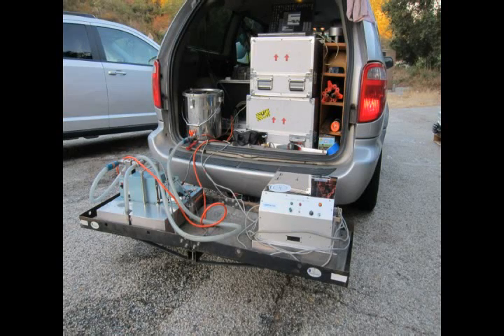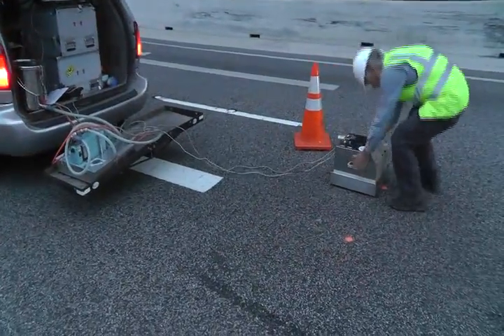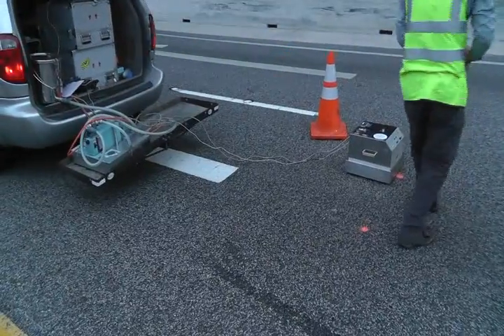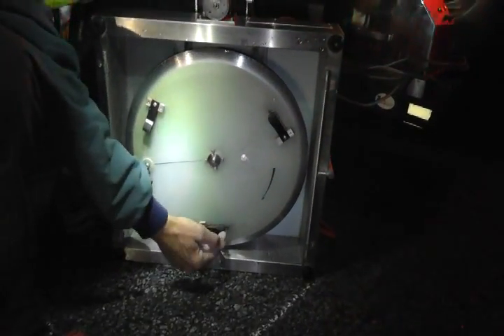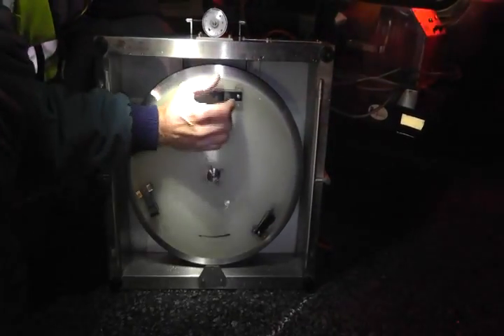This is the circular track meter, CTM, and the dynamic friction tester, DFT, which are both mounted on a removable deck located off the rear of the minivan. The circular track meter reports a mean profile depth, while the dynamic friction tester reports a friction value for various slip speeds ranging from 80 to 0 km per hour. These small pads are made from the same compounds as a rubber tire to closely simulate the existing friction condition of the roadway. Notice how it rotates in a circular direction.